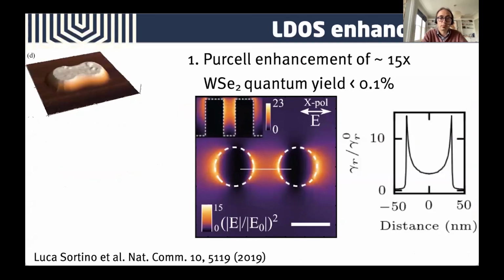And then I wanted to break down the enhancement that we get into different parts. So this is then the result of the experiments, and I will use the theory to guide you. Here we have first a Purcell enhancement of around 15 due to the effect of the density of states. So by using these nano antennas, we can enhance the density of states very much.